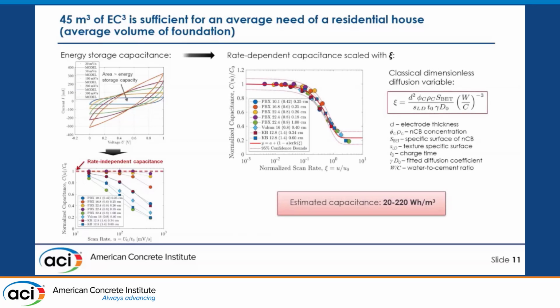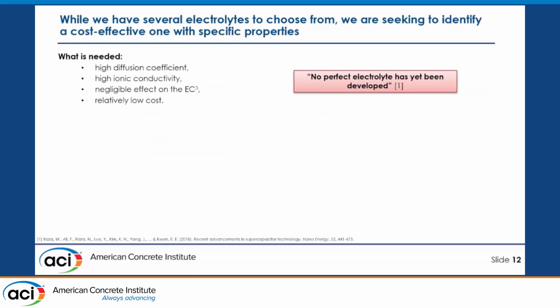Further, we show that the rate-dependent capacitance can be scaled with a dimensionless diffusion variable. We can see that all experimental results for different water-to-cement ratios, different nanocarbon blacks characterized by different specific surface, and also, extremely important here, different thicknesses and sizes of the sample, because this is a diffusion-driven process, all align with the mathematical model, the error function. Based on this we can estimate that it can store roughly between 20 and 220 watt-hours per cubic meter. I can tell you right away that this value is extremely low compared to regular supercapacitors. Nevertheless, we need to keep in mind how much concrete we use in our structures. Then these numbers can play a significant role, because 45 cubic meters of this material can be enough for the average need of a residential house. That's a very important message.